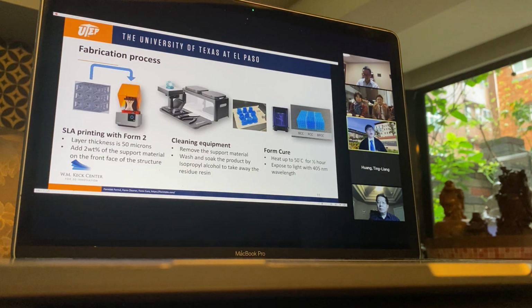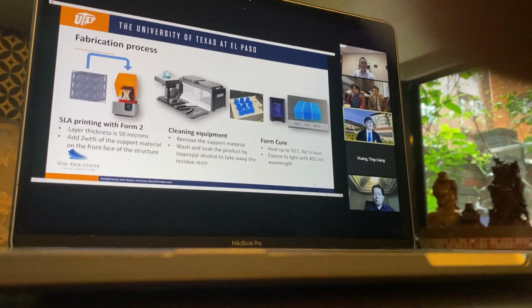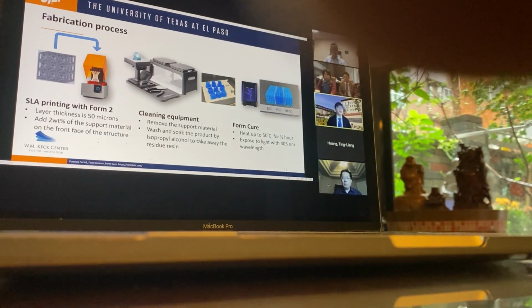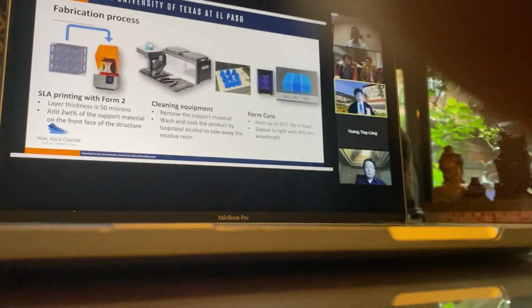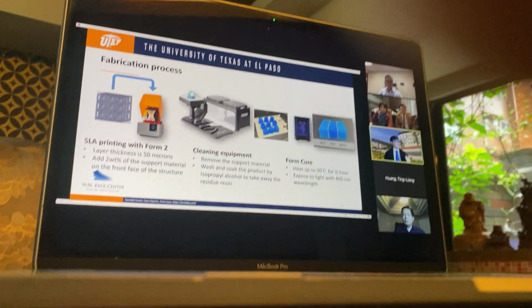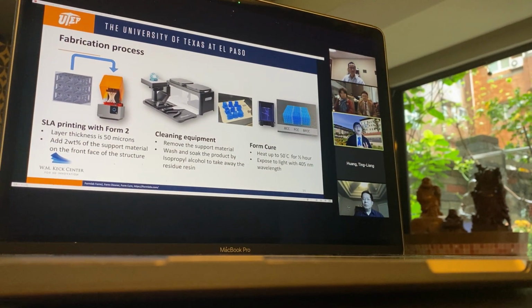So this is the fabrication process. SLA is relatively simple and convenient for us to use. To begin, we just need to import a CAD file and set the parameters of the support material, and the software will automatically generate the support material by itself. The next thing is that we set the layer thickness as 50 microns. And we need to add 2 wt% of the support material outside to ensure the printing process is stable and in case it falls down from the build plate.